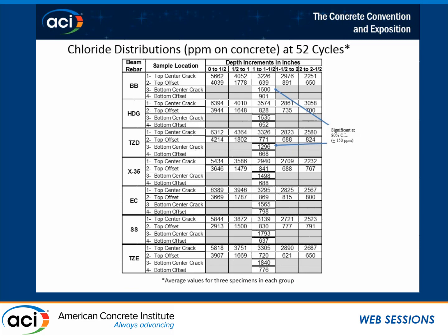Also, you can see on almost all of these, there is a decrease in chloride going through the crack for the OPC concrete. So the crack is not a direct short circuit, with the chloride coming all the way down from the surface. The crack is tapering, and there are some interactions between the cement phases and the chloride coming down, so you don't exactly have uniform chloride going throughout. And this will be important when I talk about some of the alternative cements.